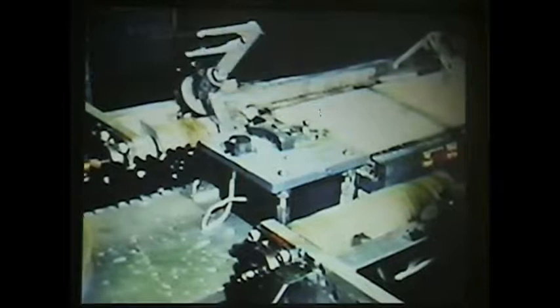Now the wafer handler comes and picks the developed and post-baked wafer into the etching tank. Here is the actual trace of this etching. We call it the etch endpoint detector. When the needle goes up, that means it's time for the wafer to get out of the tank. This is how we optimize the etching process time for each wafer. That is the reason why we can estimate what the yield should be.